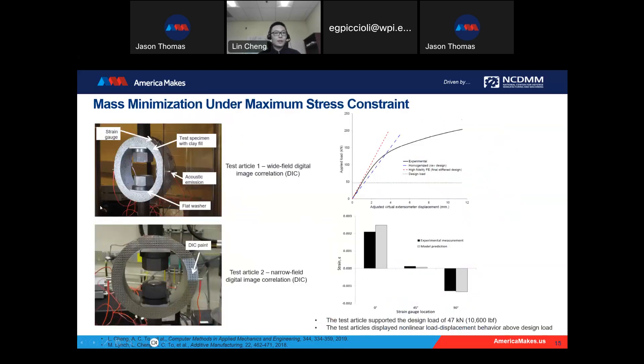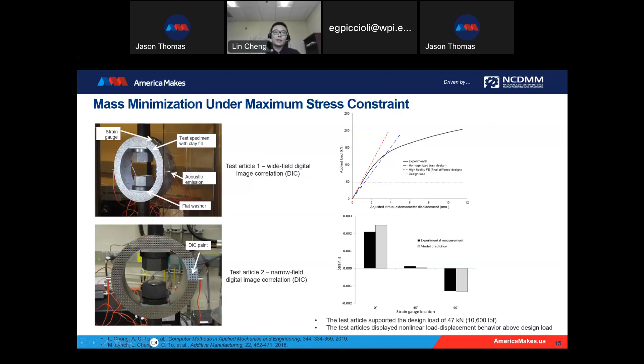Then we do experimental testing. The experiment is done by UTRC. The loading-displacement curve shows the dashed line is the defined loading of 47 kilonewtons. The solid line from experiment measurement shows a linear relationship below this dashed line — meaning all components work in the safe zone. Above the defined loading, we see nonlinear behavior and plastic deformation. We confirm from experiment that the defined constraint is satisfied, and we removed more than 50% of materials.